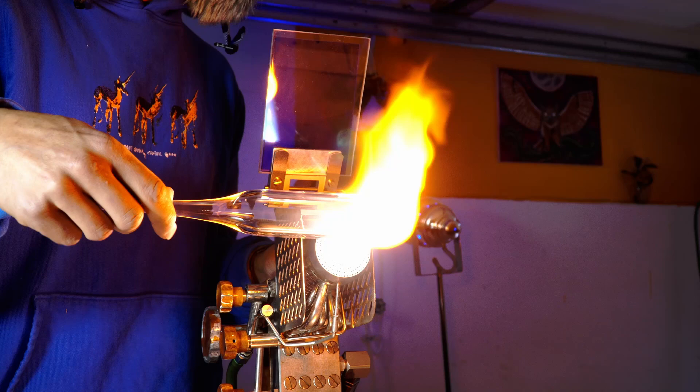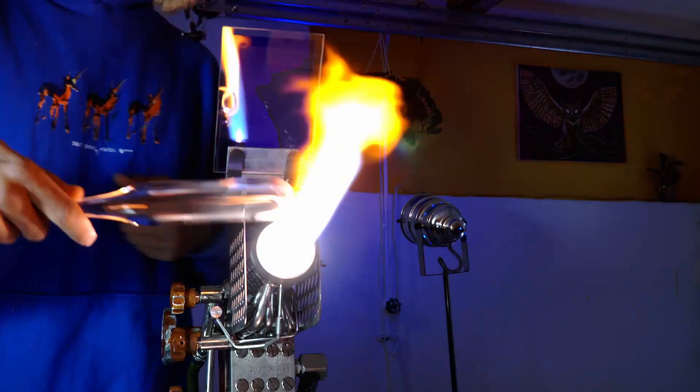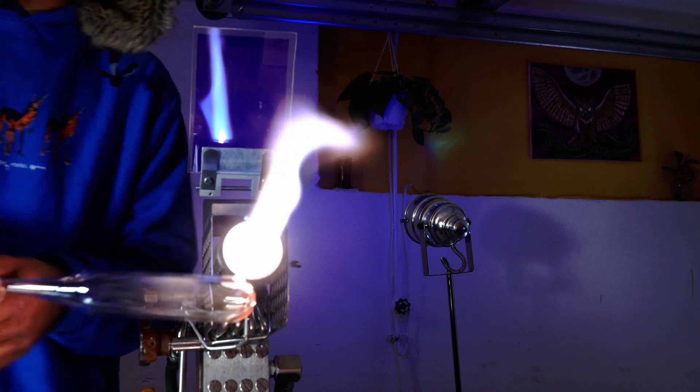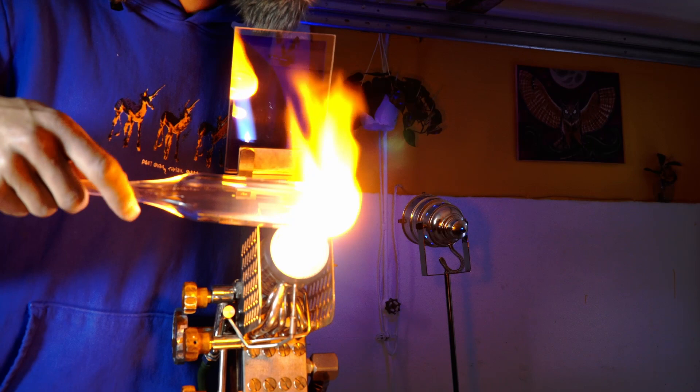And yeah, just going to bake a bunch of heat in there. Make sure it's all nice and even. You always want to keep the tip of your glass the hottest. Give it a little air and see it evens out again. And I'm gathering more glass there on the tip. Whatever's hot, the glass will follow. It's a really good thing to keep in mind.